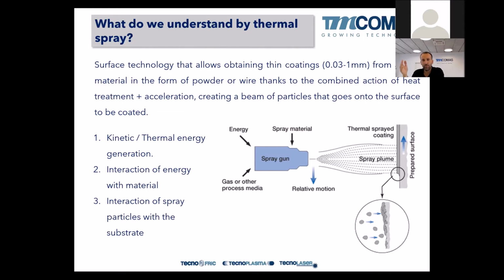So at the end, it's like painting with electrospray paint. So we are applying layer by layer onto the substrate until having enough material for the application, right? So we should have some kinetic and thermal energy available in the gun to melt and accelerate the feedstock material, whether it be powder or wire. This energy has to interact with the feedstock material, and all of this takes place in the gun and during the flight of the particles to the substrate. And then the last step is the interaction of the spray particles with the substrate. It's very important also how they interact with the substrate to achieve a good bonding, a low porosity, or the properties that we are looking for.